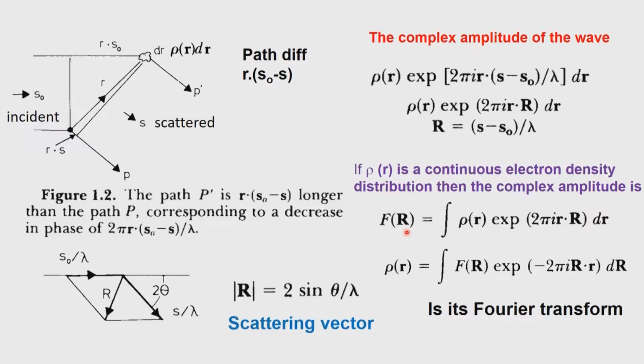And scattering is now giving a spot because of the interference rules which we have put in on a three-dimensional object. So, the scattering is now coming onto that particular spot. So, we can measure the intensity of this spot. The square root of the intensity will give F(R), but it gives only the modulus of F(R). So, we need to get the phases in, and we will put these phases in.